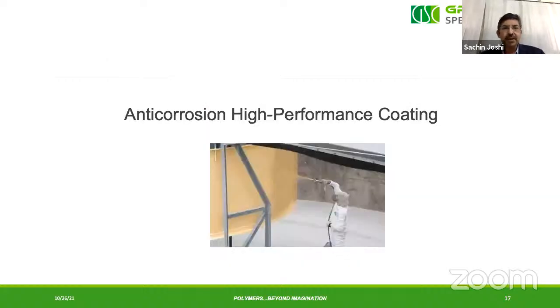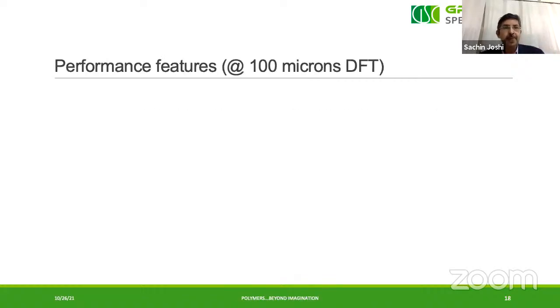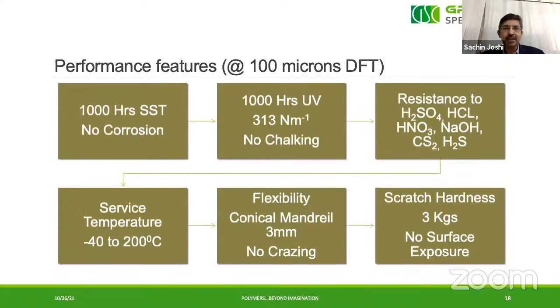So anti-corrosion high performance coating, as I said, we have tested for various properties, 6 properties, and very interestingly, it is tested at just 100 micron thickness. Now thickness is a parameter of system, it is not a parameter of performance, because as suggested, 4 coats with primer, middle coat, top coat, automatically thickness goes to 300 microns or 400 microns, and somebody skips one coat. By naked eyes you cannot measure it, so always thickness has been measured. So it becomes a parameter of system.